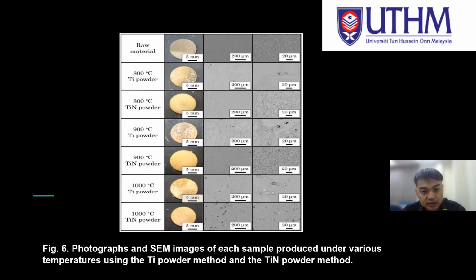Figure 6 shows the photograph and SEM image of each sample produced under various temperatures using the Ti powder method and the TiN powder method. In the Ti powder method, a circular structure was observed regardless of the holding temperature, but it was not seen in the TiN powder method at 800 degrees Celsius or 900 degrees Celsius.